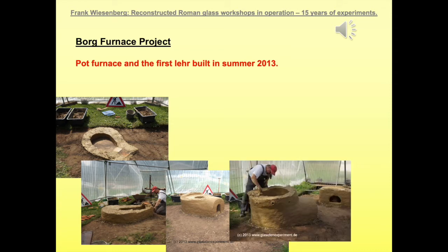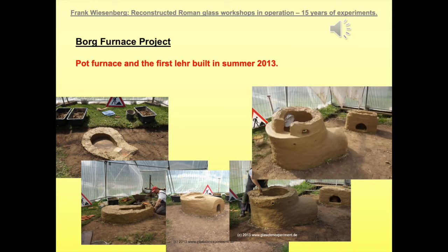During the building of the glass furnace, I added a couple of holes just above the shelf level, which can be used to insert a couple of thermal probes inside the furnace to measure the temperatures or record the temperatures during the operation. Since I decided not to use any wooden support for building the dome of the glass furnace, which could cause a lot of cracking due to the shrinkage of the daub while drying out, building the dome, including the openings for working holes and preheating holes, was the most complicated part.